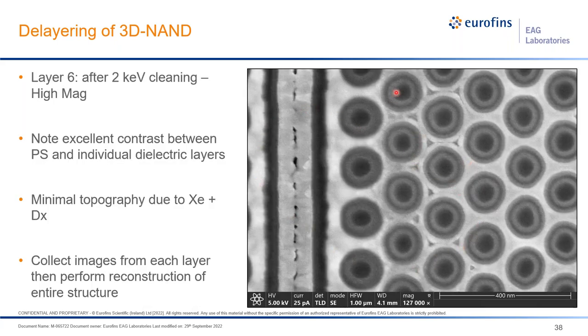And so here in high mag, we can start seeing details of the device structure and really note the excellent contrast between the individual elements in the structure, between the gate structure and then the inner dielectrics, et cetera. We can see there's porosity or voiding in certain areas. And so this kind of information is very important to understanding process development, et cetera. And really there's very minimal topography due to the use of the xenon plus the DX. And so what we're going to do is then from a region maybe a little bit bigger than this, collect images from each layer and then perform a reconstruction similar to the.